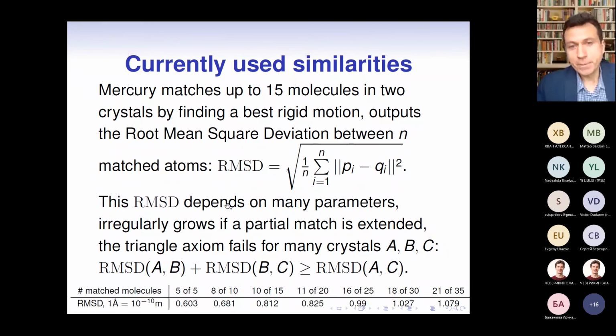There are also tolerances for distances, angles. So there is dependence on many parameters, and this small table at the bottom shows that if we increase the number of maximum matched molecules, then this RMSD value simply grows irregularly, and it's not clear what value to take as a distance. And actually, if you consider RMSD as a distance, it fails the triangle axiom that should be satisfied for all crystals A, B, C, but we have checked on experimental crystals, so on many triples, this triangle axiom fails.